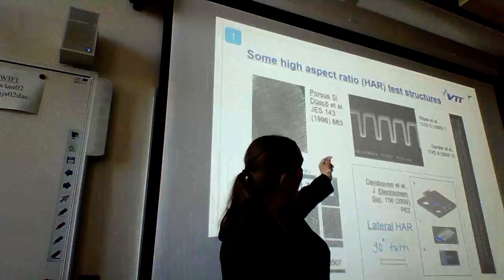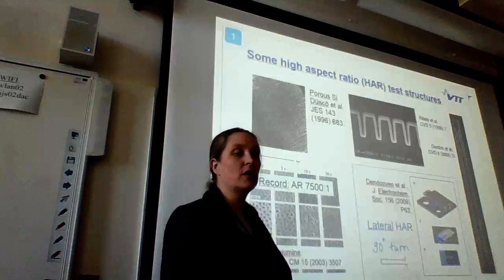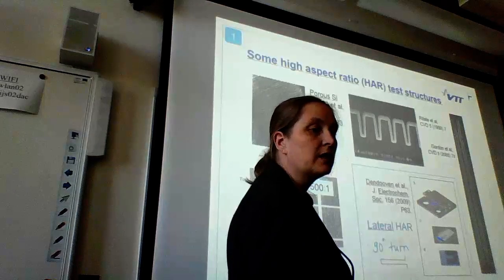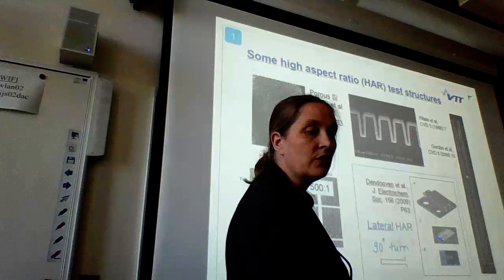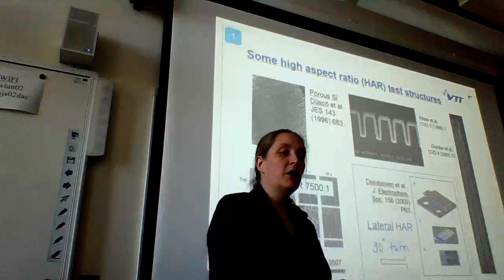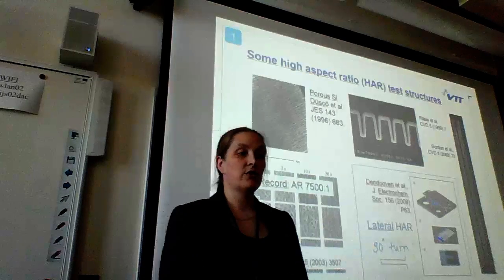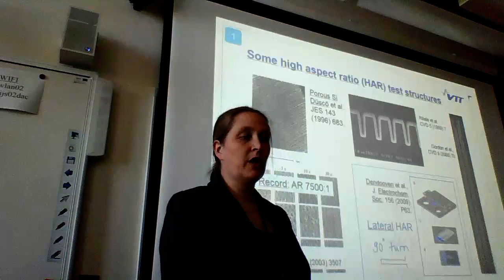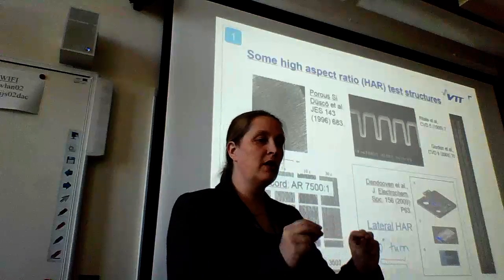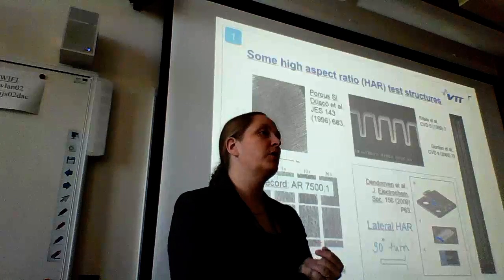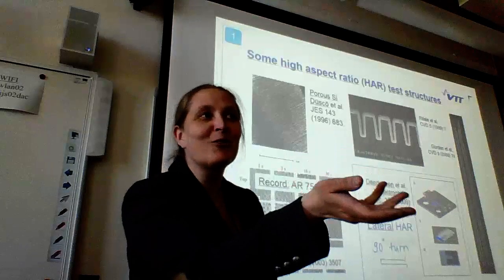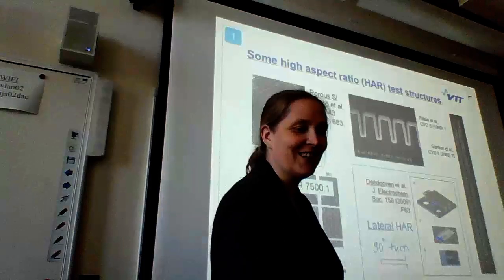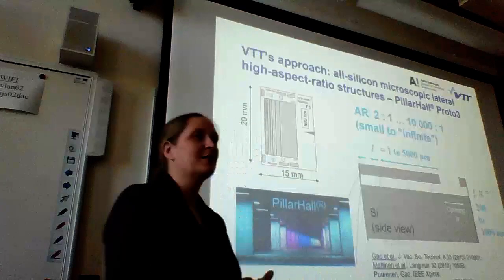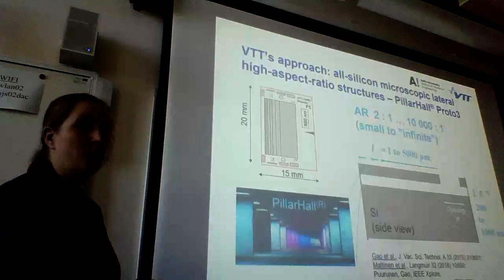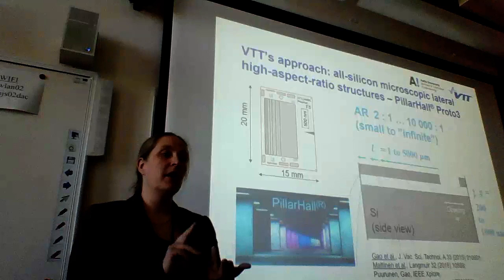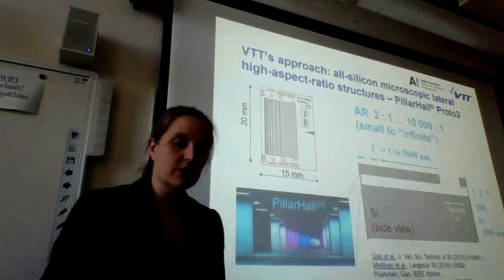Then very typically trenches or holes are etched into silicon, and earlier they were not so very demanding. This is something like 5:1, and here is already 40:1. And then also we are working with lateral high aspect ratio test structures, and also in Belgium there is a group working with these bigger ones, macroscopic self-built screwed things, but we are working with microscopic structures. You there, are you also from this group? Yes, I thought so. Professor de Tavernier's group, yes. So VTT's approach at the moment are all silicon, microscopic, lateral high aspect ratio test structures.